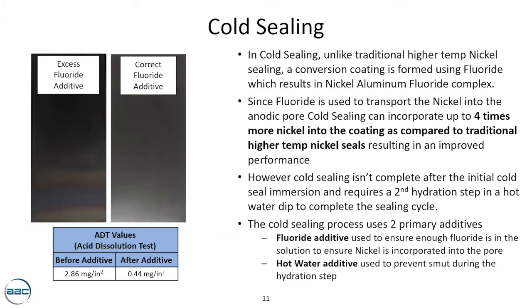Now, when you've followed up a cold seal with that hot dip, you've essentially achieved what a mid-temp and hot nickel seal try to do in one tank in 10 to 15 to 20 minutes. So the resulting phenomenon here is a process that is much more robust, incorporates a tremendously large amount of nickel, and gives you a process that is much more reliable in terms of heat consumption from heating the tank.